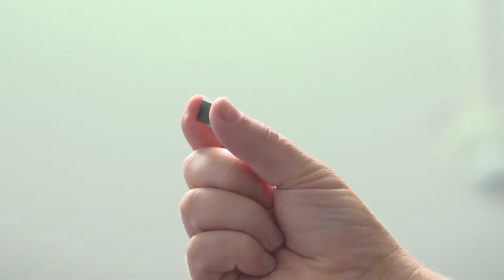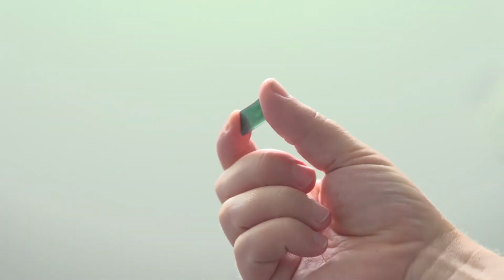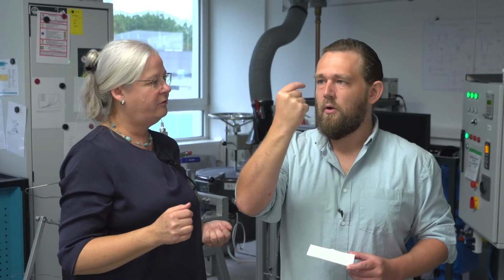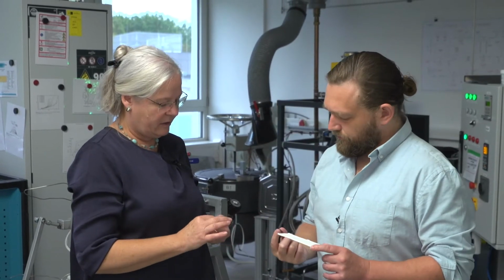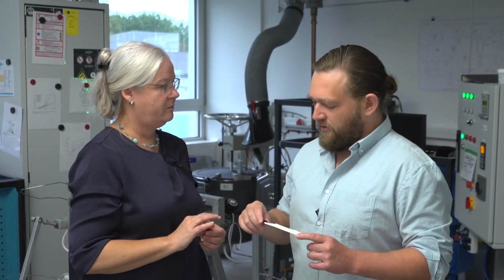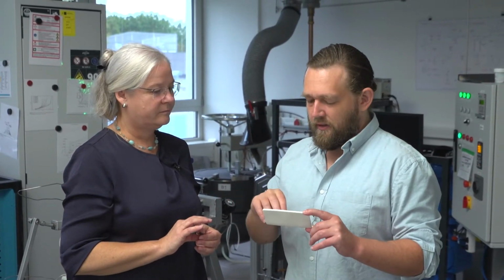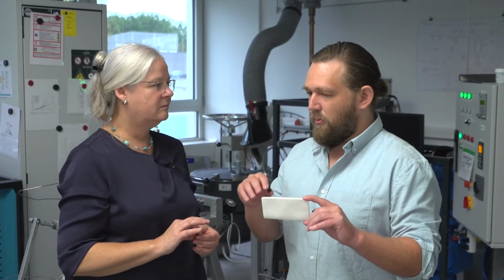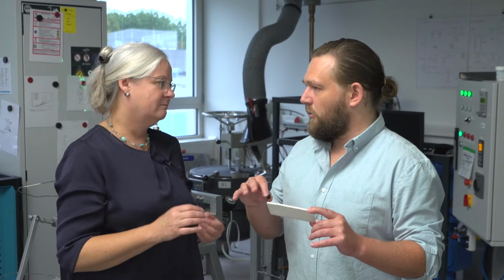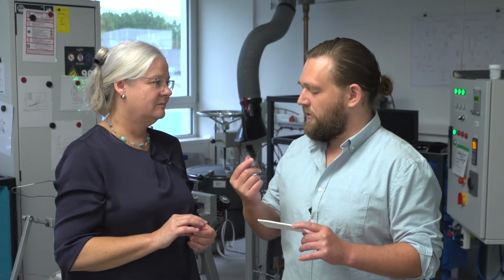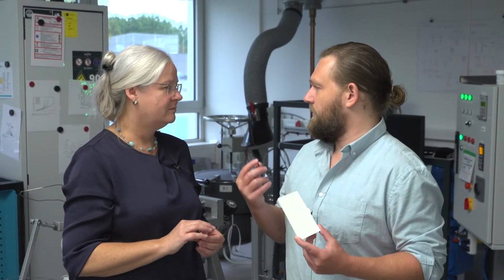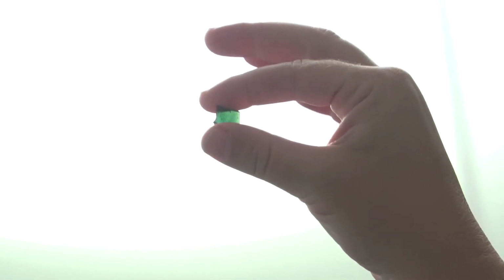This is only a small broken thing because it was tested already. And the tensile strength is much higher than the material itself. It is higher than the cellulose for sure. And it is higher than the polymer. So it sounds like this is transparent while this is not. I guess because the index of refraction of cellulose is very different from air. So with all the tiny nanopores, the light moving through it scatters quite a bit. But in here, the index of refraction of the polymer, I guess, is similar to the index of refraction for the cellulose, so light can pass through it.